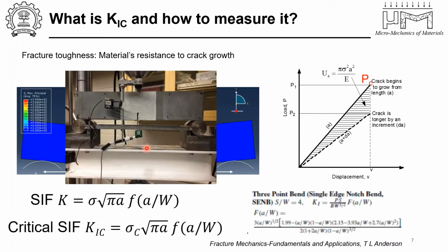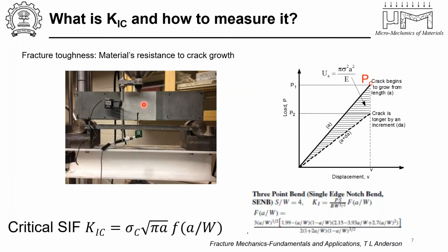So I will just show how you measure a fracture toughness from that. So you load such a specimen, and you see that it breaks at a critical load. If it's a linear elastic brittle material, then you would just see a linear elastic load displacement response and then a fracture point. That critical load gets converted to critical stress, and the corresponding critical stress intensity factor is called otherwise the mode 1 fracture toughness of the material. So basically, we are trying to measure the material's resistance to crack growth and not to crack initiation. So you already have an initial crack that is set up in the material.